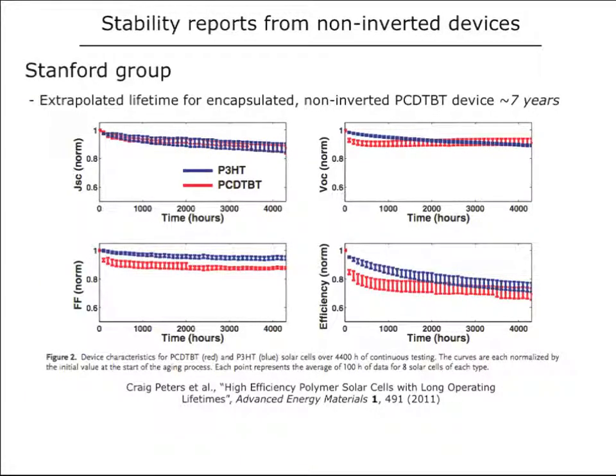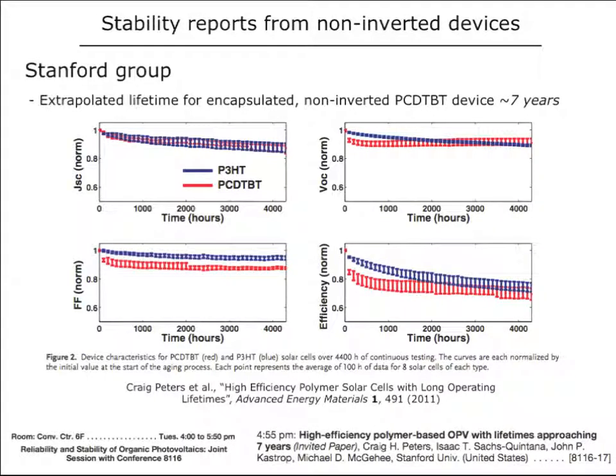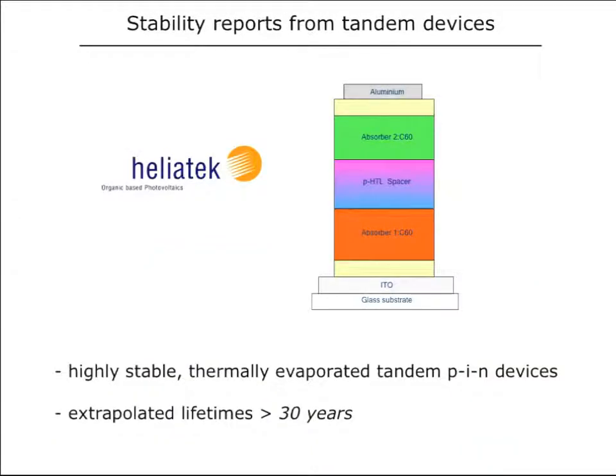The Stanford group is now demonstrating extrapolated lifetimes beyond 7 years. This is a non-inverted device. And I refer you to Craig Peters' talk, which I believe is later this week on that topic. And then finally, the Heliatek group is extrapolating enormous lifetimes for these devices, greater than 30 years from a small molecule device. So we have reason to believe that if you remove all solvent from the device, if it's thermally deposited, you get really robust devices.